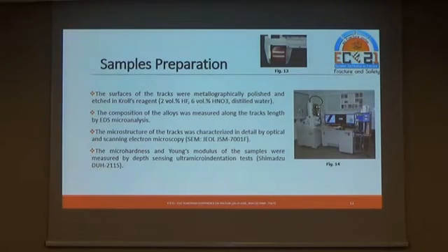The surface of the tracks was metallographically polished and etched in Kroll's reagent. The composition of the alloys was measured along the track's length by EDS microanalysis. The microstructure of the tracks was characterized in detail by optical and scanning electron microscopy. The microhardness and Young's modulus of the samples were measured by depth-sensing ultra-microindentation tests.